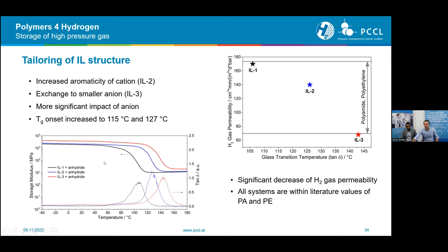To this end, you can see here two more resins, IL2 and IL3. Internally, of course, the number is a lot higher, but those are the most promising resins. For IL2, we increased the amount of aromatic groups in the resin itself, in the cation. And for IL3, we exchanged the anion to a smaller anion. As you can see in both the dynamic mechanical analysis and the permeability measurements, the anion has a very significant impact on both permeability and glass transition temperature. And here we reach a very high modulus and very high glass transition temperature with this anhydride hardener. However, as you can also see from those literature values, all the systems are within common materials for liners.